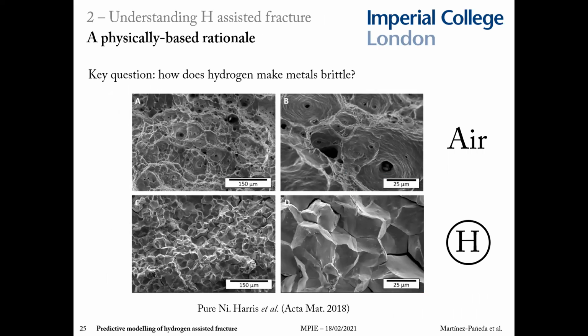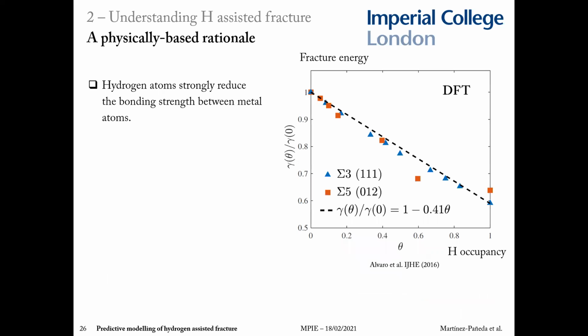And now this takes me to the second research front, which involved gaining mechanistic understanding into the process. And the key question here is to understand, how does hydrogen make metals fail in a brittle manner, often with the crack propagating along the grain boundaries, as you see in that slide. For this purpose, I tried to determine what were the first order effects behind the ductile to brittle shift that we see in the presence of hydrogen. I came to the conclusion that 3 ingredients are key to develop a mechanistic rationale.